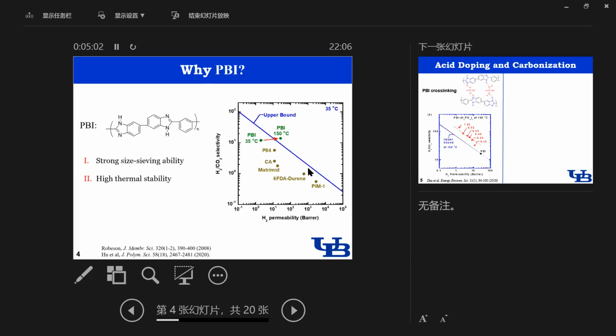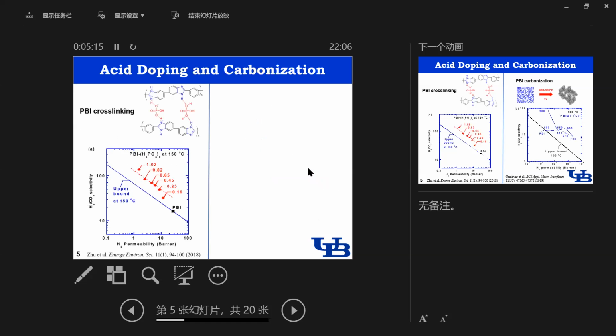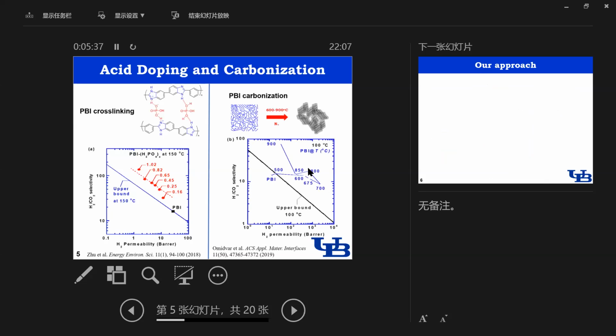But the hydrogen permeability or hydrogen CO2 selectivity is too low to use in practical application. So we once tried using phosphoric acid to dope PBI, and we got high hydrogen CO2 selectivity above 100. But there is a trade-off between hydrogen permeability and hydrogen CO2 selectivity. We also once carbonized pure PBI, and we got some good performance at high carbonization temperature. But high carbonization temperature always means bad mechanical stability.